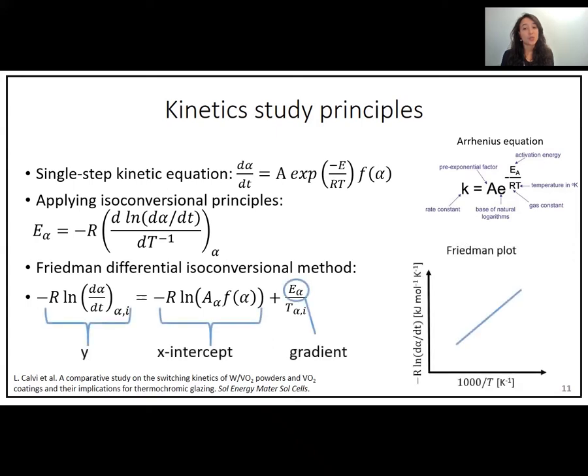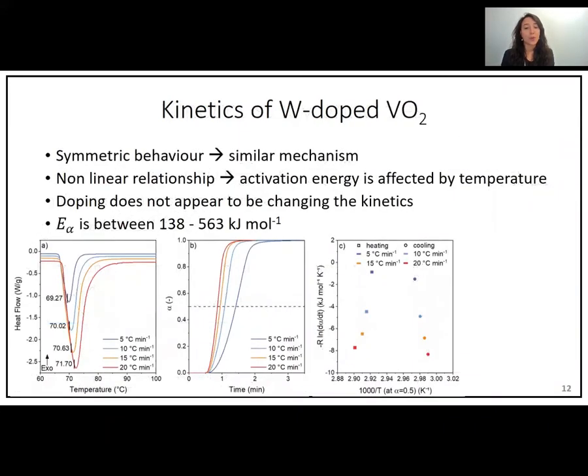This equation is used to derive the Friedman plot, in which the conversion rate is used and the corresponding temperature at this rate. The gradient of the Friedman plot results in the activation energy for the structural phase transition. So now, combining all the previous equations and the running integral of the vanadium dioxide at various heating rates results in the Friedman plot, which is illustrated here on the right. We can see that the plots are almost symmetric, and also they are non-linear.